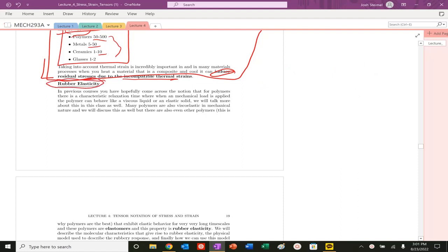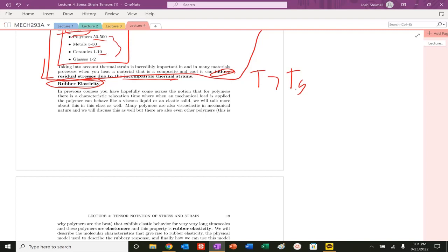But for materials, especially polymers where our temperature is greater than Tg, the glass transition temperature, that behavior is actually going to be dominated by the entropic response. Specifically, we're going to see a type of entropic spring-like restoration force that leads to elastic behavior.